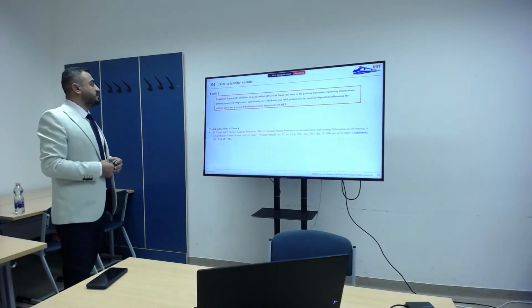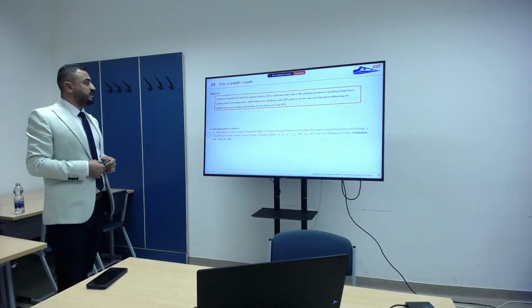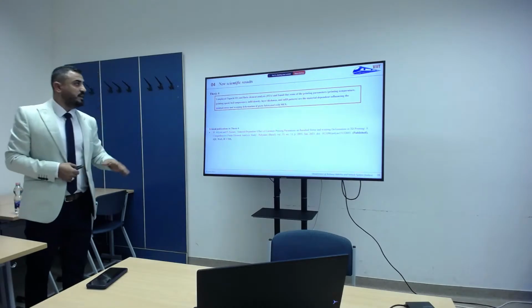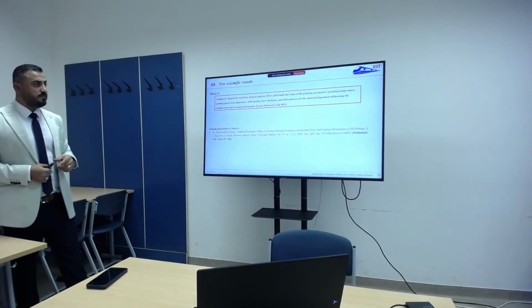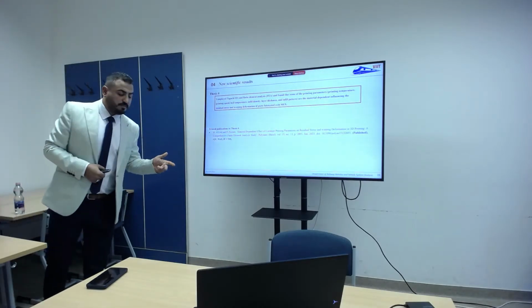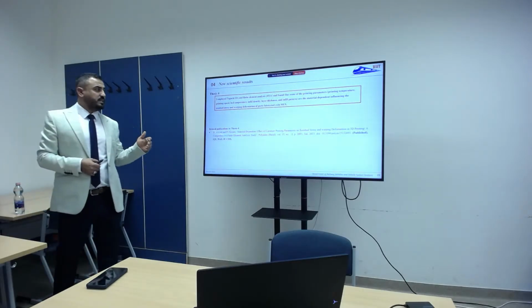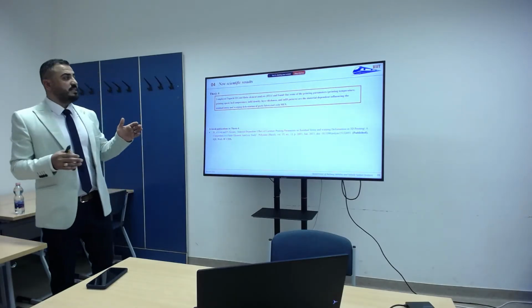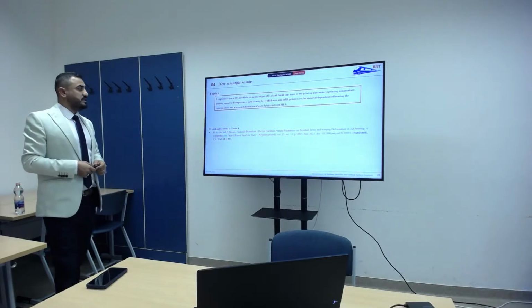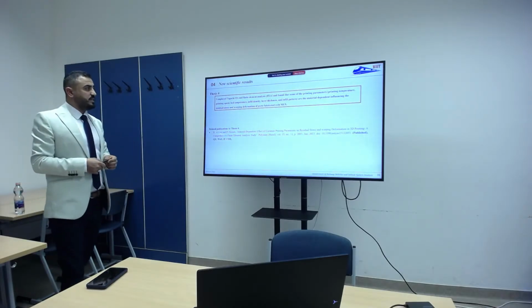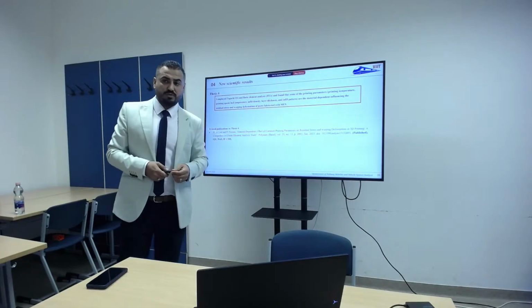So thesis number 4 stated that I used the Taguchi orthogonal array and finite element analysis and found that some of the printing parameters, printing temperature, printing speed, bed temperature, infill density, layer thickness, and infill pattern are material dependent, influencing the residual stress and warping deformation of parts fabricated with the material extrusion technology.